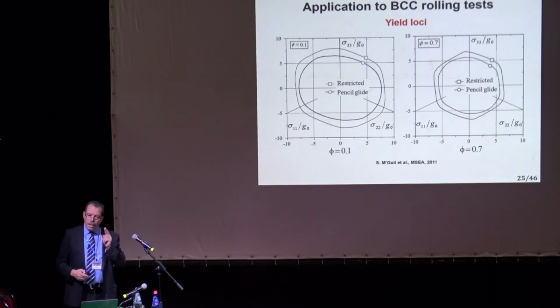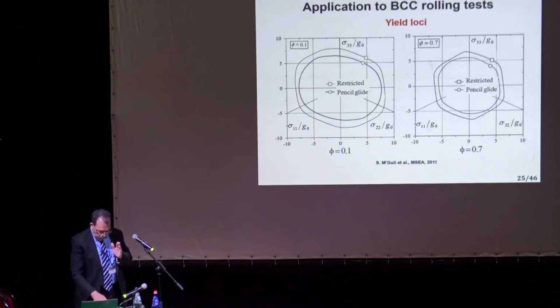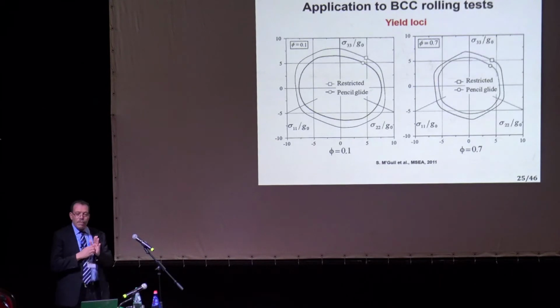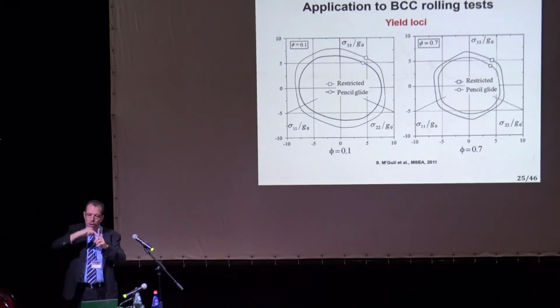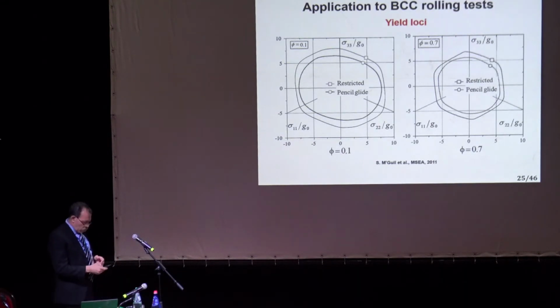However, there are also other planes, and there is also even what we call the pencil glide, which is the 111 direction. We are sure it's the slip direction, and it could be any plane around that 111. So we call it the pencil glide. Okay. So here we did not take an infinite number. What we took is the 110 planes, the 112 planes, and the 123 planes that are major ones that are known, and that's what we call the pencil glide, just to have more kinematic freedom somehow. Okay, you have more systems of deformation. But anyway, just to show you that with this type of model, we can also predict the yield surfaces, okay?